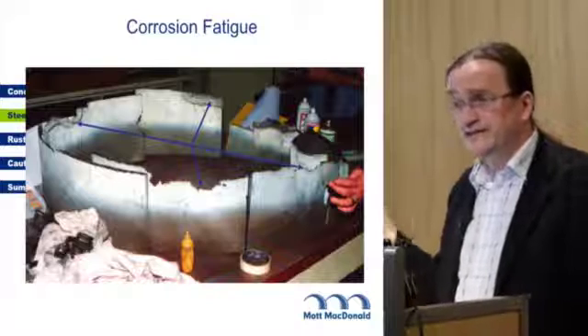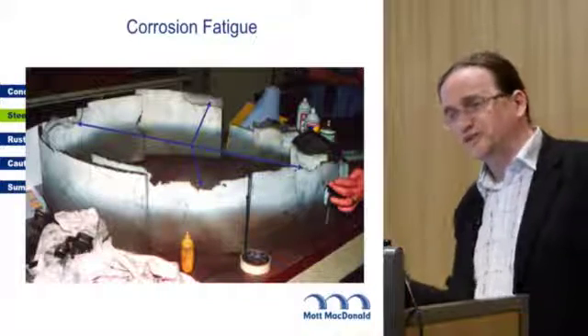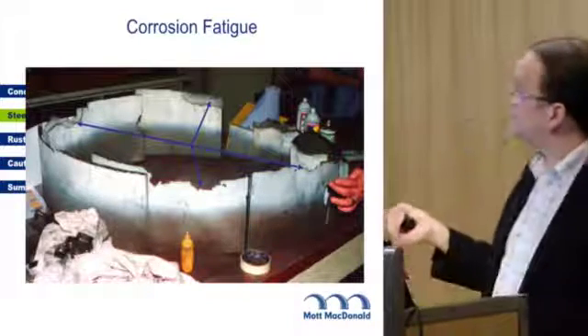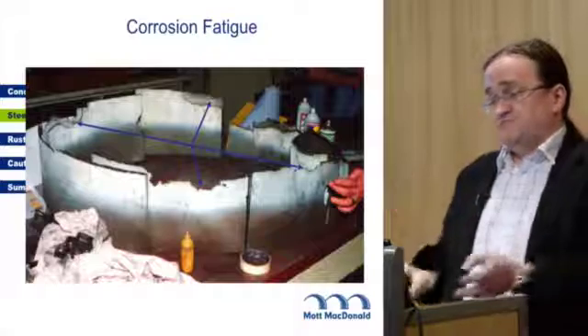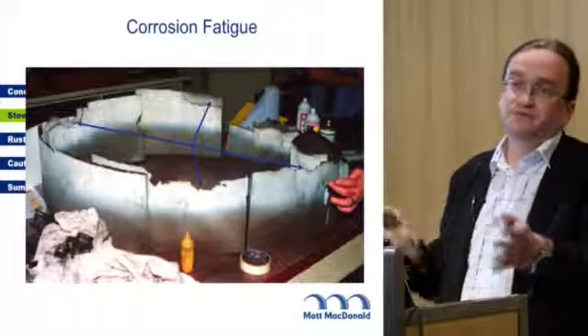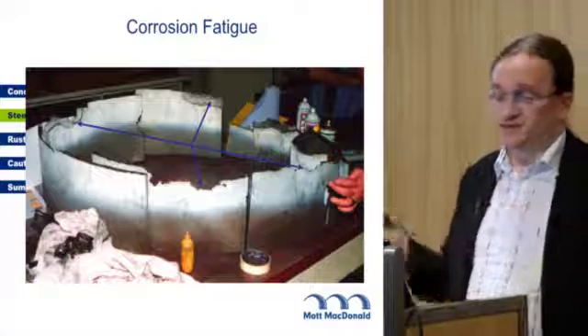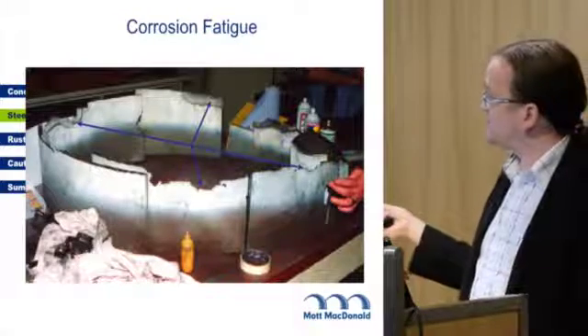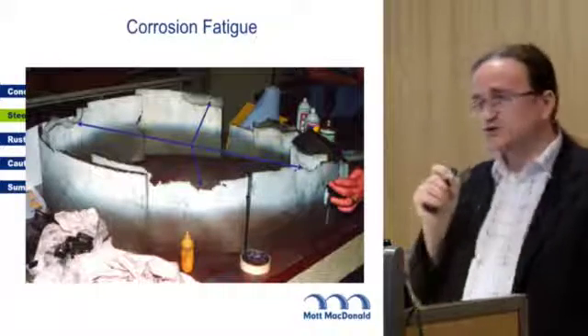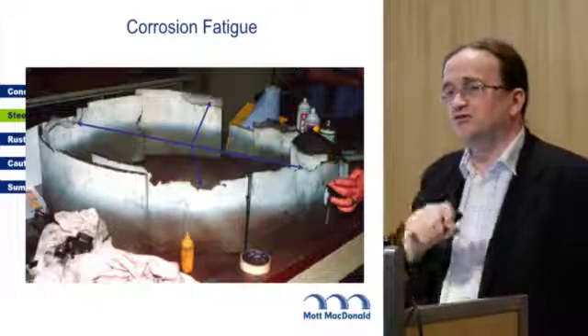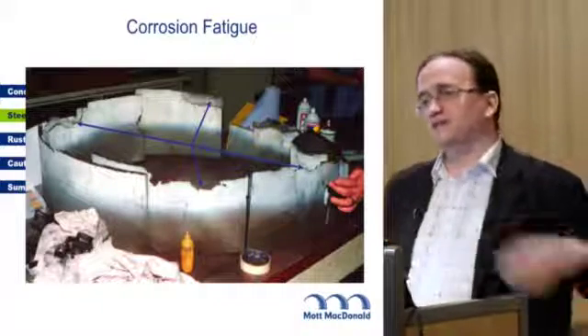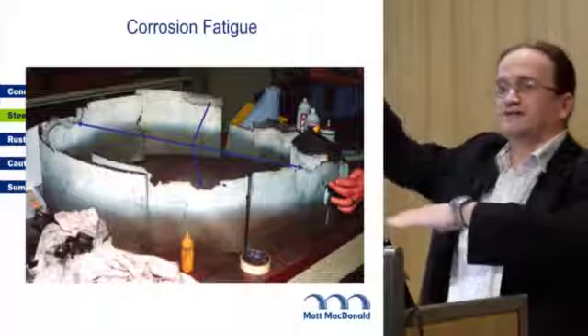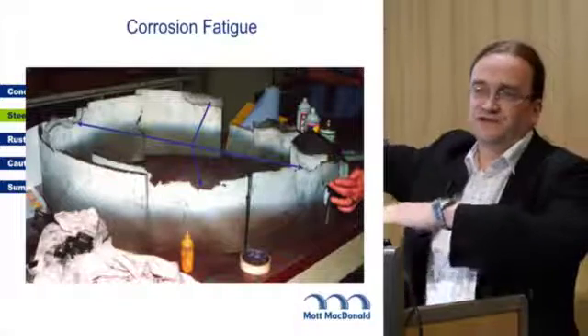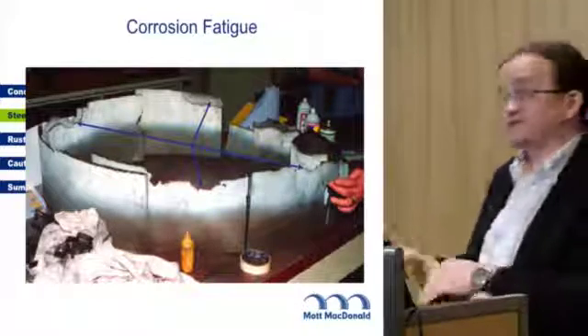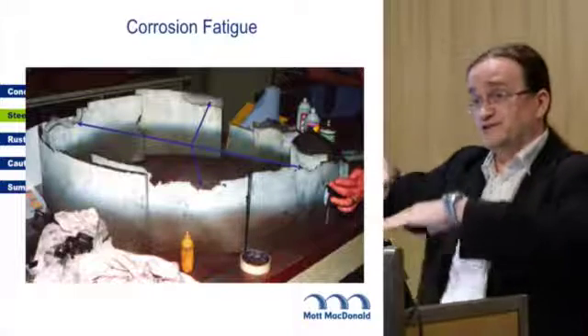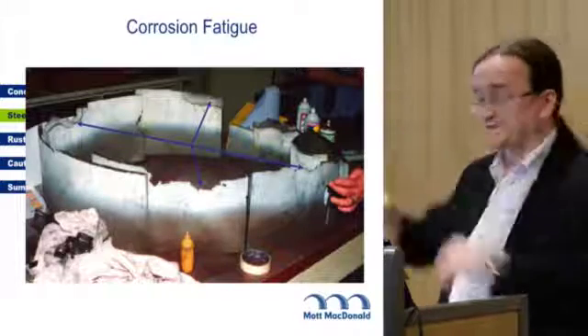Anyone who deals with fatigue, there's a little side arm that the corrosion engineers throw at you called corrosion fatigue. Cyclic stress, corrosive environment. Cyclic stress gives you fatigue, corrosive environment gives you corrosion. It's quite difficult to distinguish from plain fatigue, but there is one subtle difference. There's no stress limit. Normally, if you're not sticking something above a stress limit, fatigue doesn't happen for steel. Aluminium's not the same, it doesn't have a stress limit, but for steel, as long as you don't put it into that region, it's not going to fatigue.